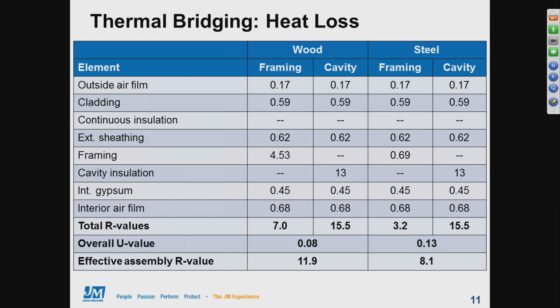And what the method lets us do is treat the framing areas of a wall and the cavity areas of a wall separately, and then later take an area-weighted average of the two to determine what the overall performance is. So as we work from top down in the table, from the outdoors to the indoors, we start off with an air film, which gives a very small amount of insulating benefit. Then we have exterior cladding, and of course this number could really vary widely depending on the materials that are used. In this example, we're not using any continuous insulation. Then we next have our exterior sheathing, which would be exterior gypsum board, plywood, OSB, any sort of material like that we'd put on the outside of a building.